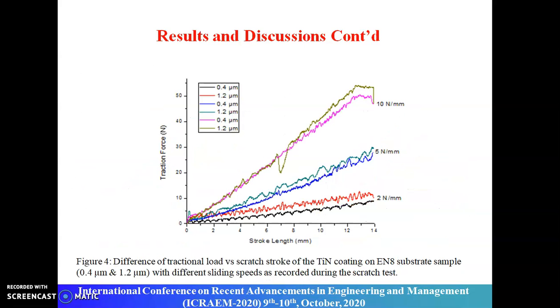Next slide. The scratch test results indicating the values of traction force at various stroke lengths are illustrated in figure 4. For the EN8 substrate, the traction force increased linearly with an increase in the stroke length. The step-like behavior of the load variation and scratch track obtained on coating, the waviness in the shape of the curves, decreased with an increase in the indenter normal loads. The greater slope of the traction force curve indicates that the share of elastic deformation increases with the increase in stylus depth.